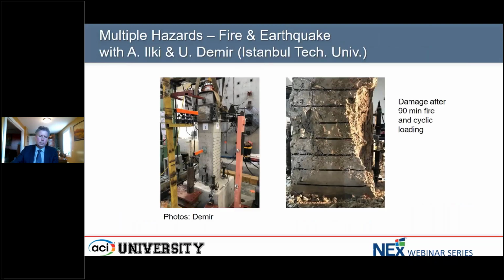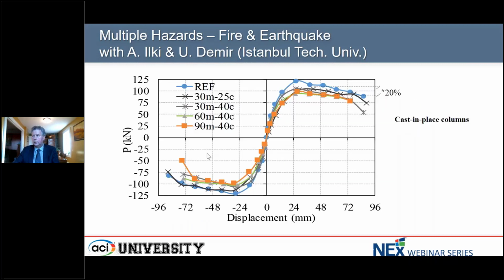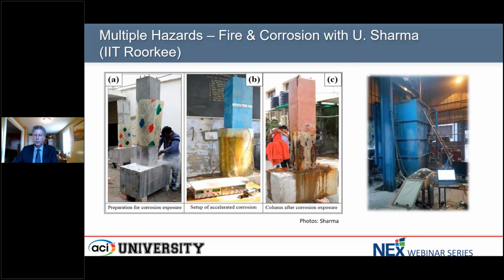And so if we move on to other multiple hazards now, we've also been looking at combining fire with earthquake. In these cases, what we looked at is we provided some fire exposure, and then after we did the fire exposure, we performed some cyclic tests, and we found that yes, the fire exposure does change the behavior in the earthquake, but at least for the exposures that we had up to 90 minutes, so not as much fire exposure as you might think, the seismic behavior was still fairly reasonable in those cases. Some of my colleagues in Turkey at Istanbul Technical University did that work with us.